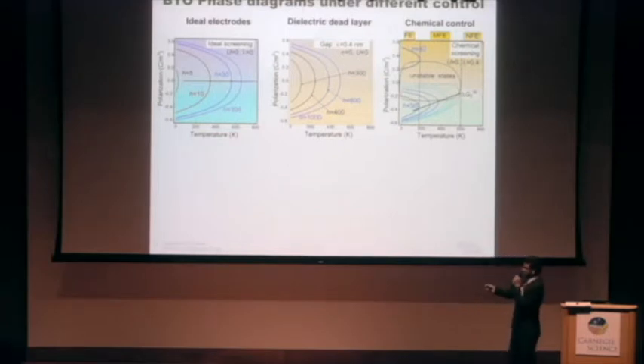And so you can see this here. At high temperature, of course, it's paraelectric. At low temperature, there is a polarization that's stable here, and a polarization that's stable here, so that checks out. But in this intermediate range between 200 and 600 Kelvin, you can see that there's a large region where there's only one stable polarization state.